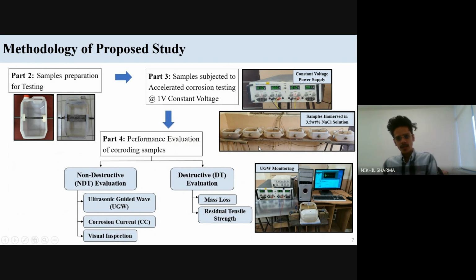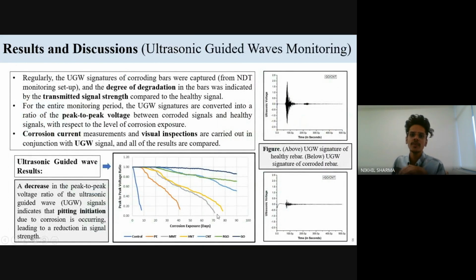These results were evaluated by non-destructive and destructive monitoring. Non-destructive monitoring involves ultrasonic, corrosion current, and visual inspection, whereas destructive monitoring is mass loss and residual tensile strength. The major part of the non-destructive monitoring is ultrasonic guided wave monitoring, in which the healthy bar signal is on the right side of the slide. With the initiation of corrosion, the signal is degraded, and once the rebar is completely corroded, the signal strength is completely depleted.